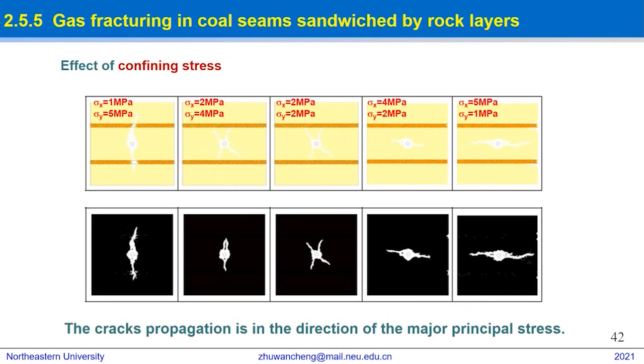The numerical simulations under the lateral pressure coefficients of lambda equals 0.2, lambda equals 0.5, lambda equals 1, lambda equals 2, and lambda equals 5 are given, respectively. As the lateral pressure coefficient increases, the horizontal geostress is larger than the vertical one, and horizontal fractures are easily induced. Compared to hydraulic fracturing and gas fracturing, high-pressure air blasting more easily penetrates hard rock layers and produces more complex cracks, so it can more effectively enhance the coal seam.